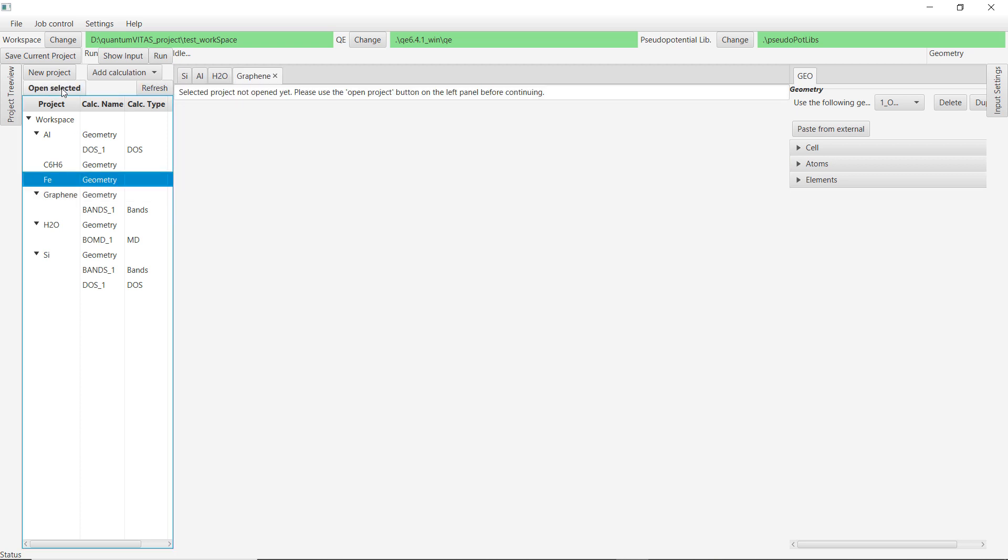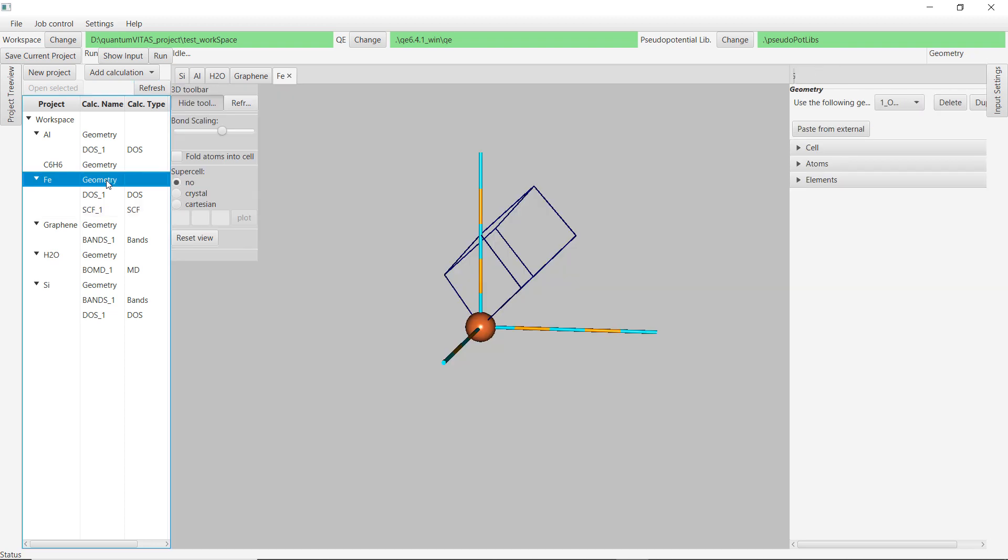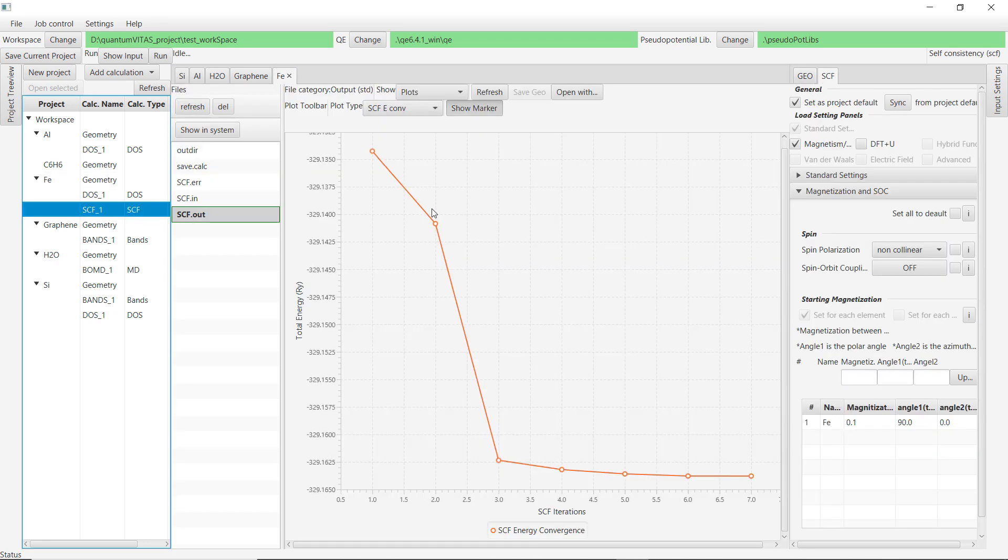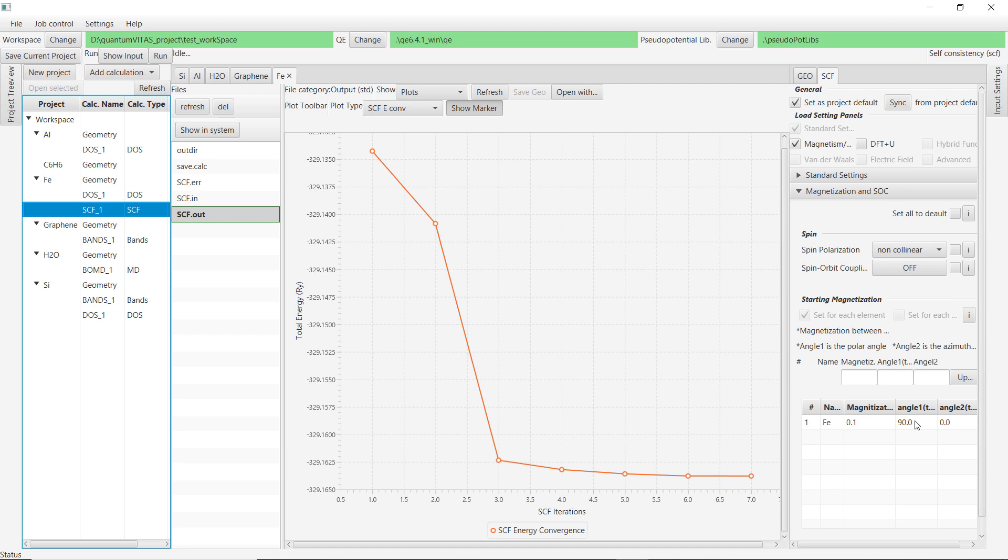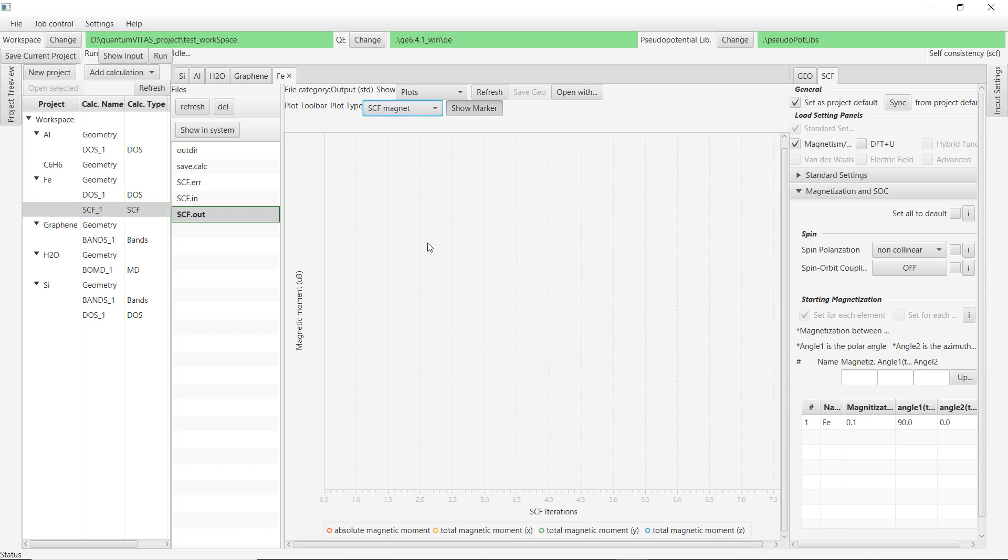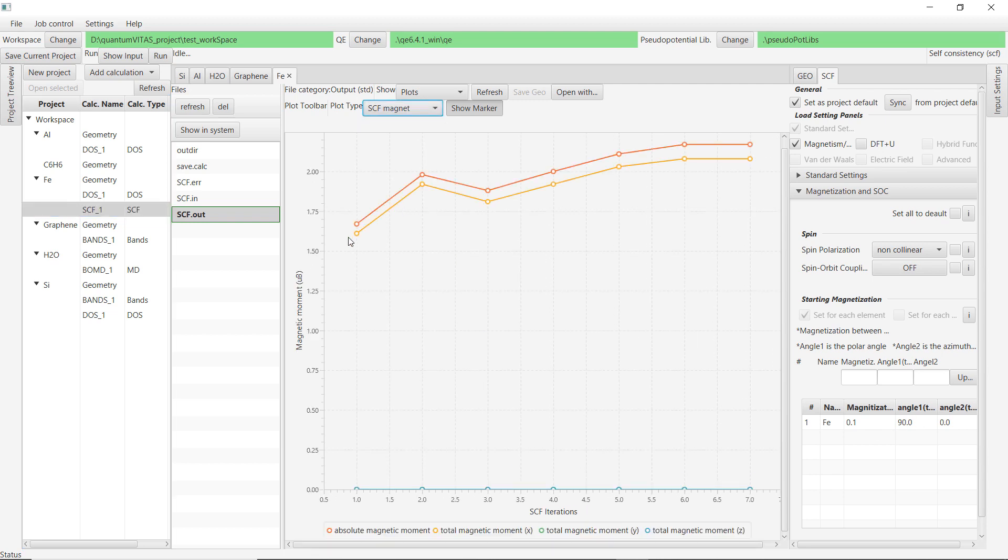We could not only do non-magnetic calculation, we could also calculate magnetism. So this is iron. We could again translate that to the conventional cell so that we know how it looks like. It is BCC lattice. And then first we could do self-consistency calculation with magnetism. You see here we deliberately use non-collinear calculation just to show you that it works. Of course here it does not really make sense to use non-collinear, but let's say we could calculate that with angle pointing into the x direction. And then we could see how the magnetism evolves in the self-consistency step. Here this absolute magnetism, total magnetic moment, the y and z projection is basically zero. And this means that there is approximately two Bohr magneton per iron atom in this case.